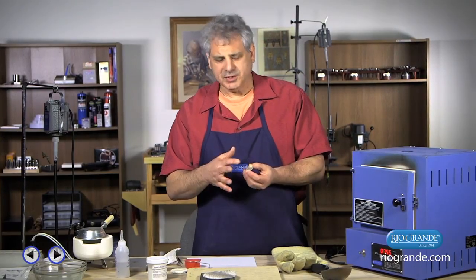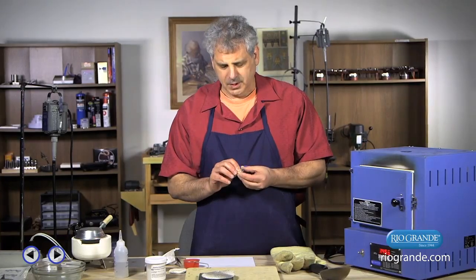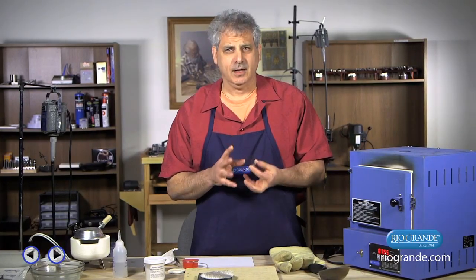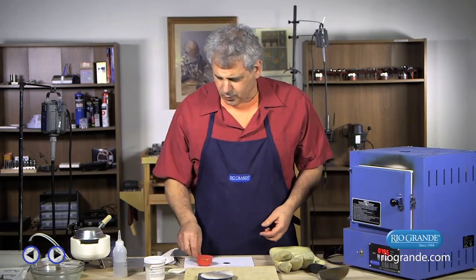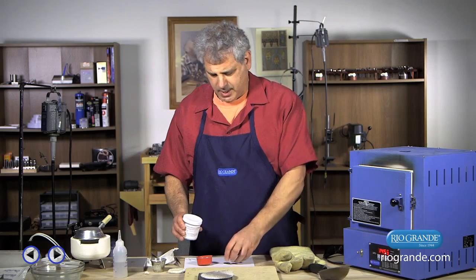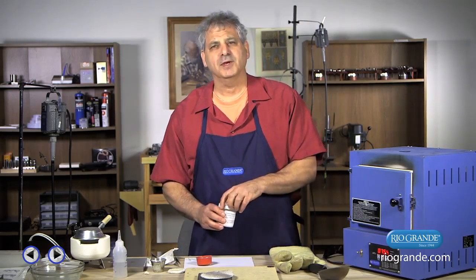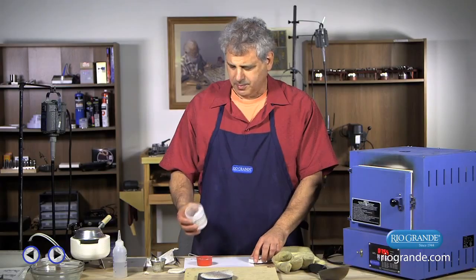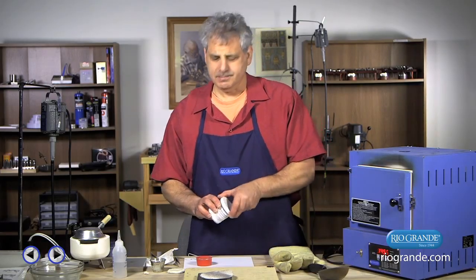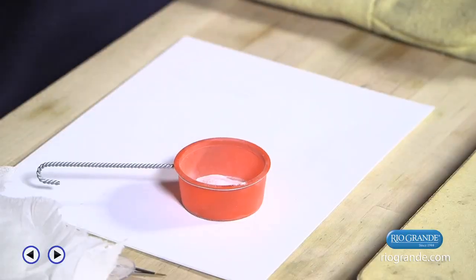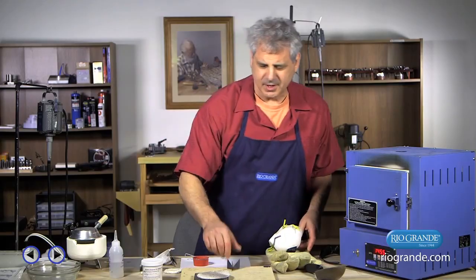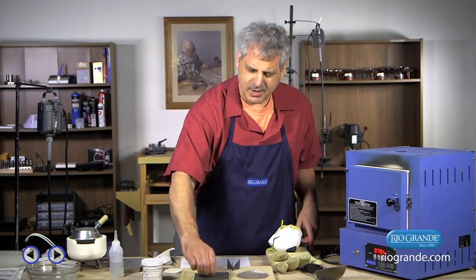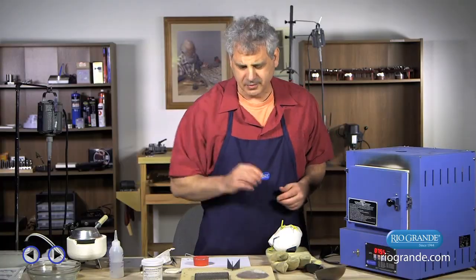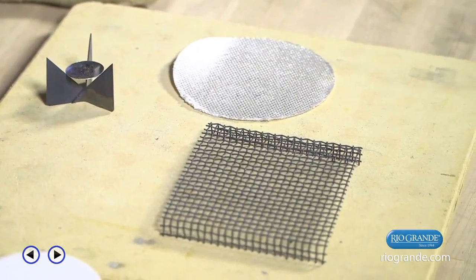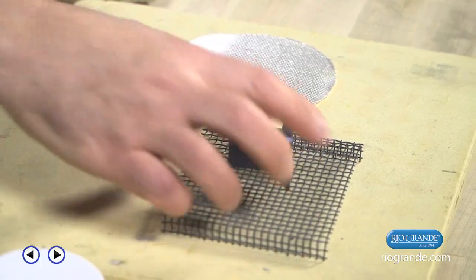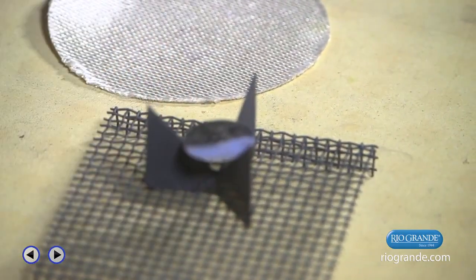Once I start adding more enamel, which I'm going to do, it's going to be too stressful. So what we're going to do is put enamel on the back, and we're going to call that counter enamel. So really any kind of enamel you want to use is going to be fine. And since I'm not worrying about this being clear, I'm going to take some unleaded opaque white, and this is undercoat white 1010, but you could really use anything. I'm going to sift this, and I'm going to use a trivet to fire this time, because if I put this on my screen, that enamel is going to melt and stick to the screen. So the trivet is going to allow the enamel piece to melt without having this stick to the screen.